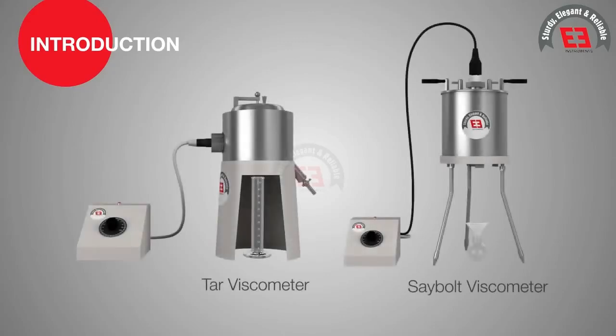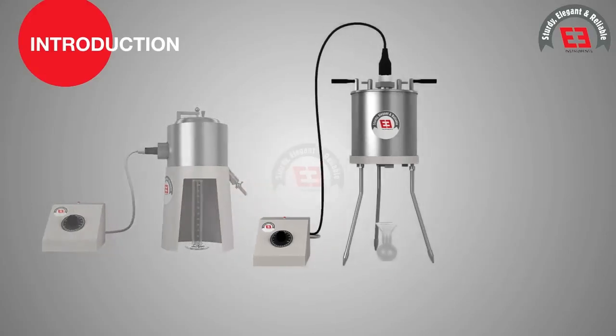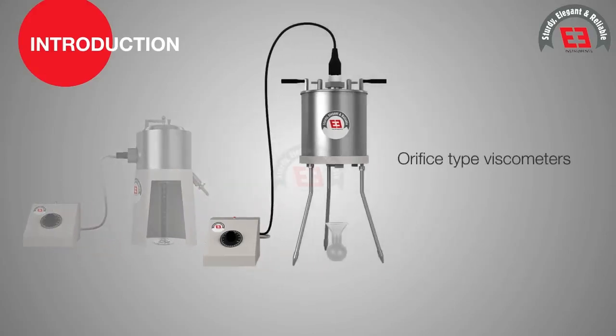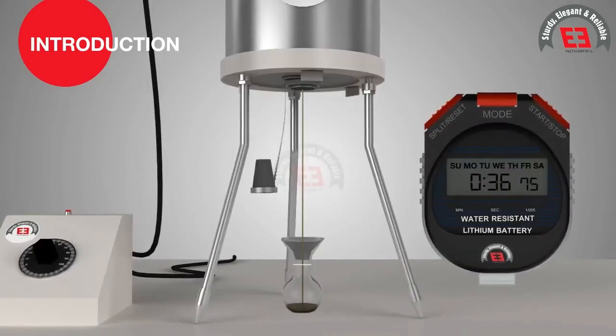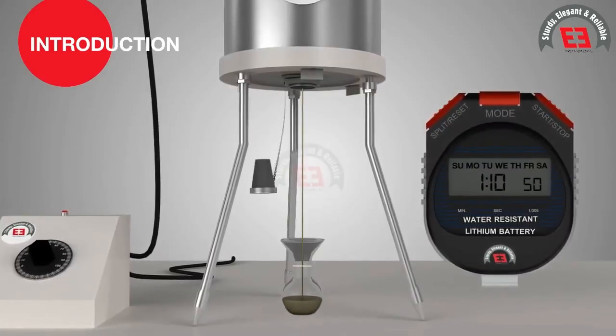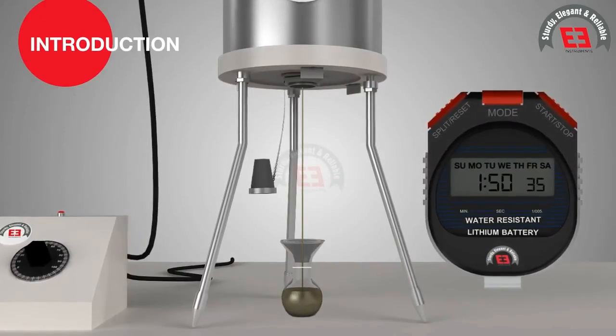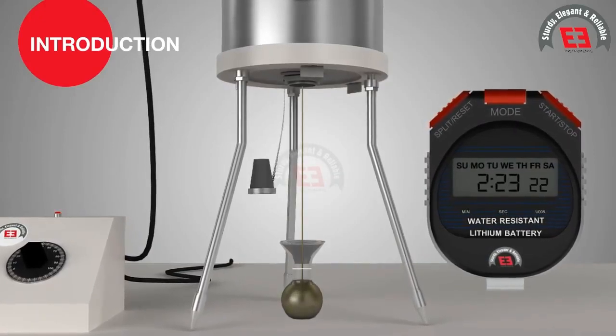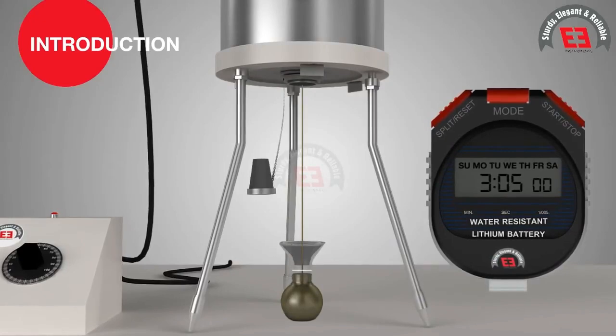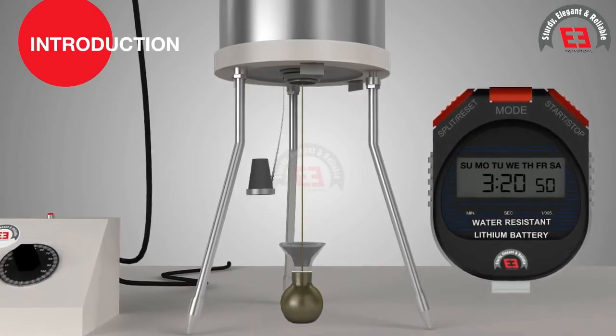Viscosity of liquid bitumen binders like bitumen emulsions and tar are determined by indirect method using orifice-type viscometers. A 60 ml of the binder is allowed to flow through specified orifice size of a cup at a given temperature, and the time taken in seconds is recorded as the viscosity value.